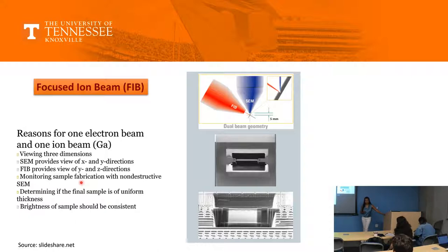Right. So he says the ion goes at a fixed distance in the material. Another reason is that it is a lot faster. Any other thing? You can definitely choose your desired grain in SEM, and you can take a sample out of it. It could be oriented in the 100 axis, 101 axis, or 111 axis, however you want. The top reason, however, nobody said. Why do we prefer using FIB over electropolishing or mechanical polishing?